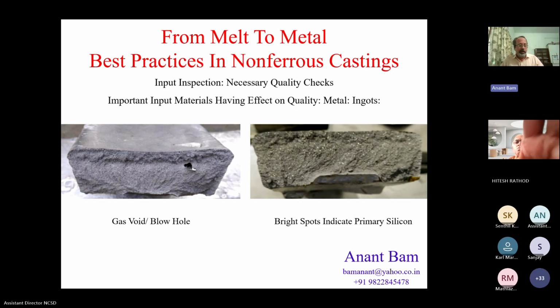There are some other defects in the ingots. On the left-hand side, you can see a gas void or a blowhole in the ingot itself. It's a harmless entity from a quality point of view, but it shows that since the gas bubble developed, the ingot mold might be wet, or the cooling water from the cooling channel of the ingot caster has entered a mold ready for casting. Otherwise, such a big blowhole cannot appear in an automated ingot casting line.